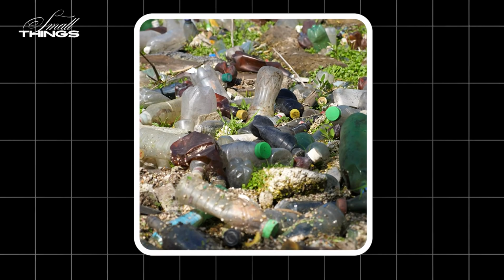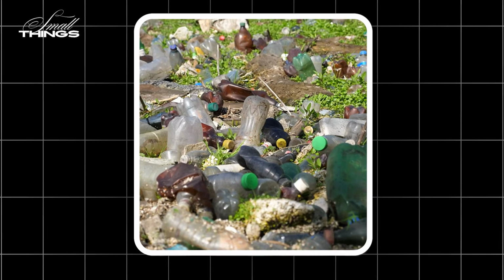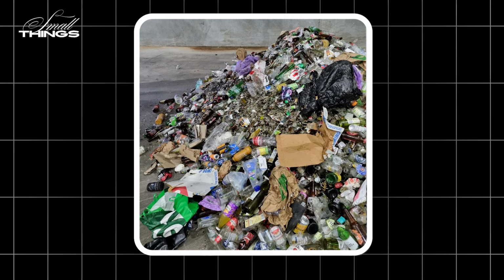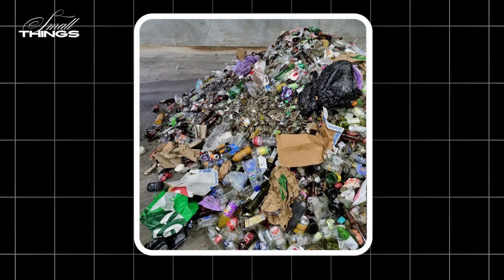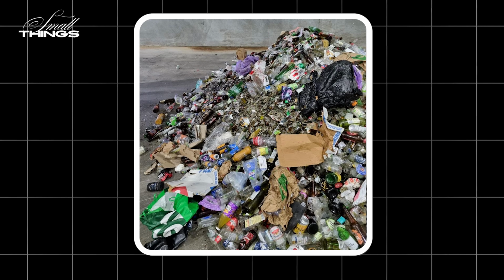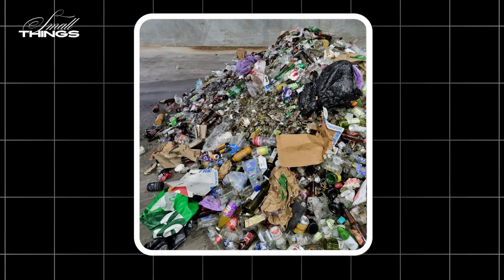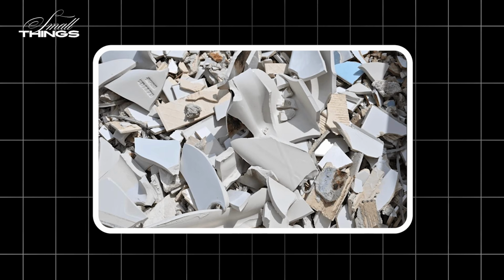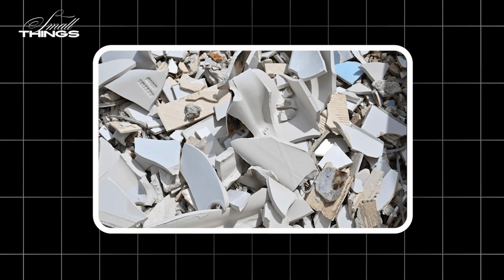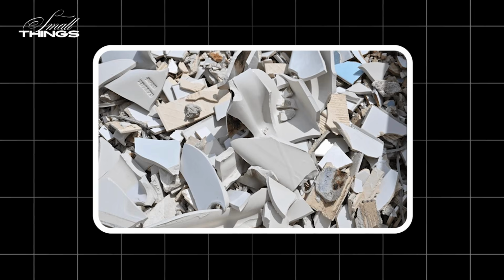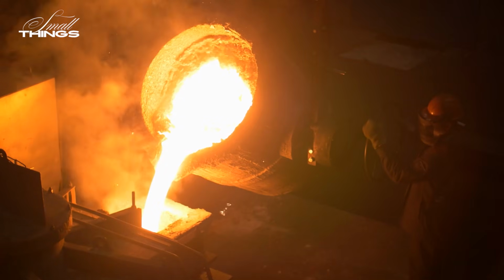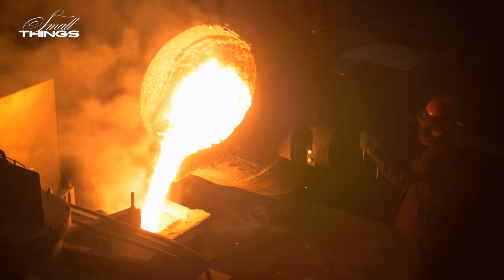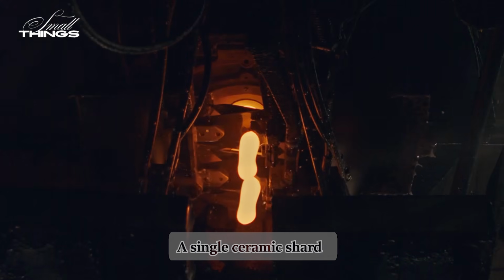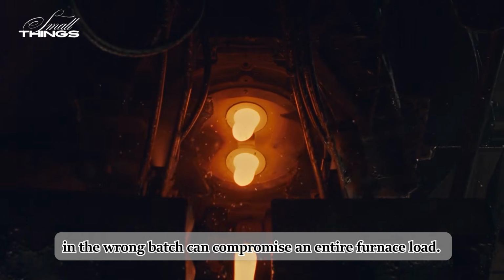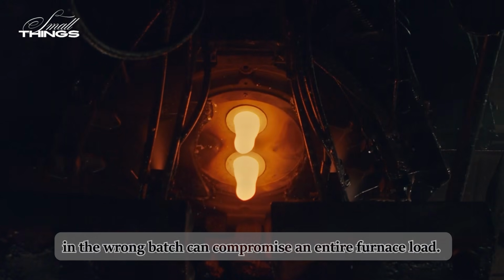Glass that arrives mixed with general household waste is a different problem entirely. It arrives broken, contaminated with food residue, mixed with ceramics and porcelain that look similar to glass but behave very differently in a furnace. Ceramics and porcelain have higher melting points than glass. They don't dissolve in the melt. They create hard inclusions in the finished product that can cause the new bottles to fracture. A single ceramic shard in the wrong batch can compromise an entire furnace load.